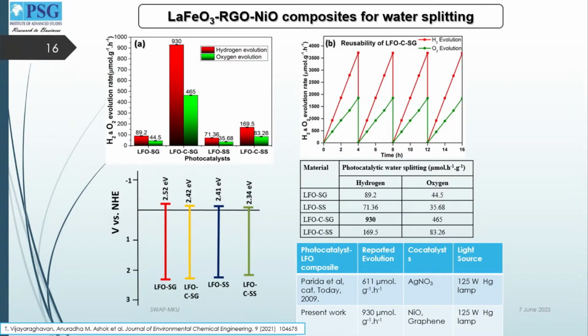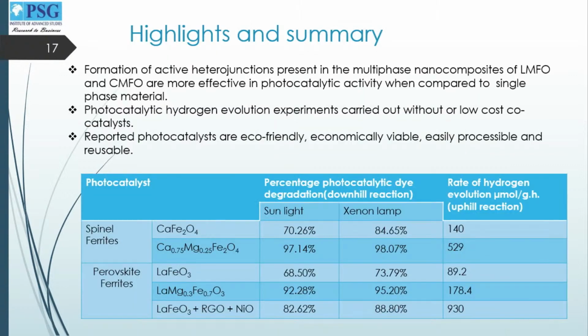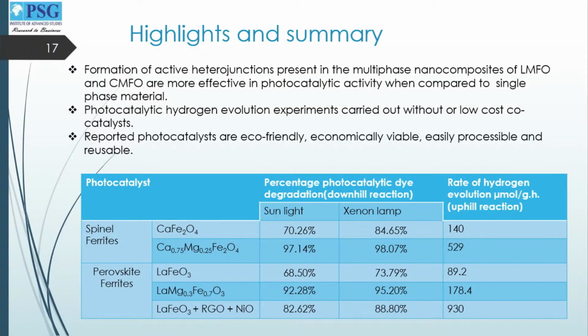We believe that because of the extra electrons supplied by the co-catalyst and also the larger recombination time in the composite form, we could get this higher photocatalytic activity in this kind of composite materials. So to summarize, through doping and also in the form of nanocomposites, oxide materials can be effective photocatalysts. Of course, we have to work more to further improve the efficiency.